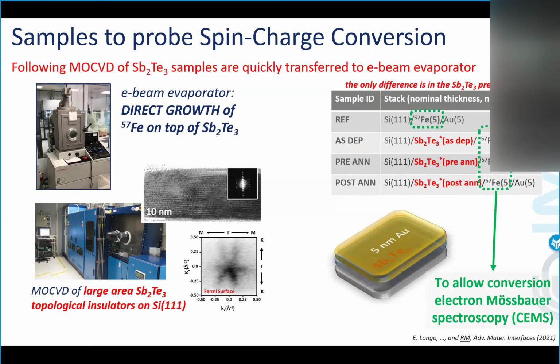Now, this is the set of samples that have been analyzed by Mössbauer, and the main difference is here in red. I don't want to go into the detail of this. I would be happy to give all the details if you are interested. We start from an as-deposited topological insulator, no annealing, no processing, no optimization. And then there is another sample called the pre-annealed, where the substrate is annealed before the deposition, and finally the post-annealed. When all this is done, simultaneously in the same growth, we grow the iron 57 and the capping gold on top of these 4 samples. So they are all nominally identical as far as the iron is concerned.